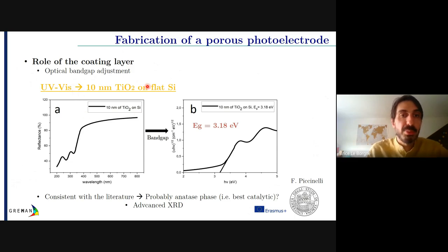So this is 10 nanometer titanium dioxide deposited on silicon. You can measure the reflectance, and thanks to a calculation, you can extract the band gap. So for 10 nanometers, we had almost 3.2 eV, which is in agreement with the literature for the anatase phase of the titanium dioxide. And now to check in the pores, we need to perform advanced XRD.